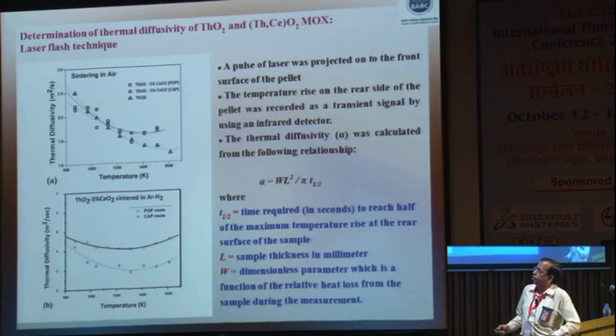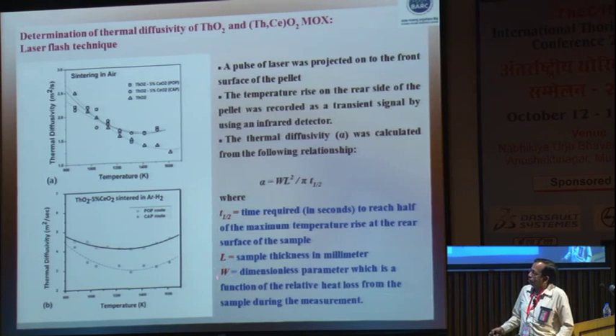Now, coming to thermal diffusivity or thermal conductivity, which has been evaluated by determining thermal diffusivity. For this, a laser flash device has been used. A pulse of laser was projected onto the front surface of the pellet, and the temperature on the other side of the pellet was measured as a function of time, and also the size of the pellet was considered, and this is a dimensionless parameter.